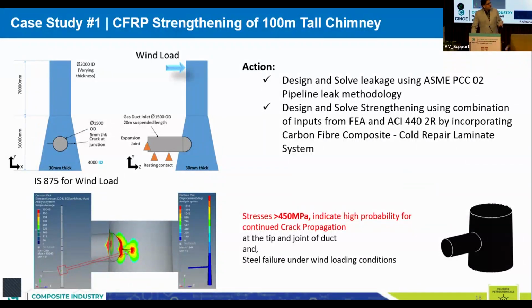And for the strengthening purpose, we used a combination of finite element analysis to identify the load paths and the stresses induced, and ACI 440.2R, the American Concrete Institute's code for strengthening of civil structures using GFRP or CFRP. If you look at the figure on the top left, it is the view of the chimney where there is an intersecting pipe creating a junction. That has created a weak zone, because under wind loads on such tall structures, there is a deflection in the chimney. That deflection combined with its inherent degradation of the wall thickness led to propagation of a crack at the bottom left. Now, if you see the stresses, they are exceeding 450 MPa already in steel, which is already gone. And cracks don't stop. They continue to expand.